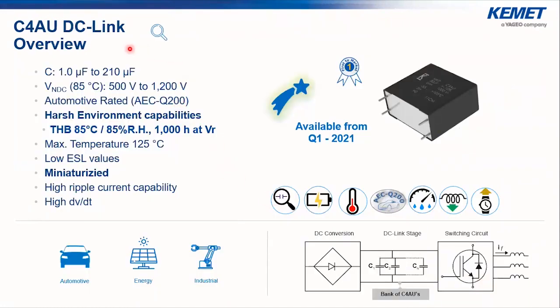C4AU has a wide range of capacitance values starting from 1 to 210 microfarad with a rated voltage range from 500 to 1200. It's fully automotive, AEC-Q200 qualified, and this DC-link design has high capacitance density, low leakage current, low losses, excellent self-healing capability, long operational life, and it's really able to withstand high power and high ripple current, a large amount of charge-discharge cycles, and it's able to operate reliably, safely, in harsh environments.